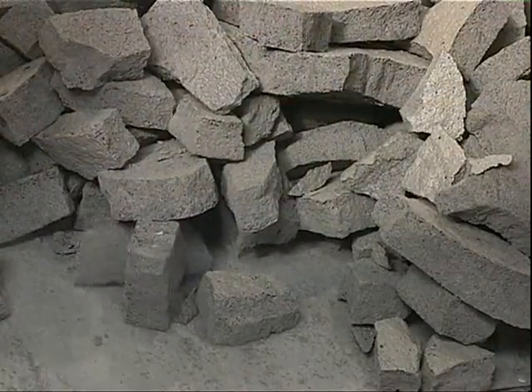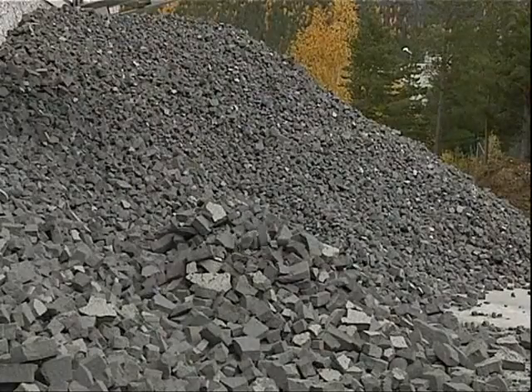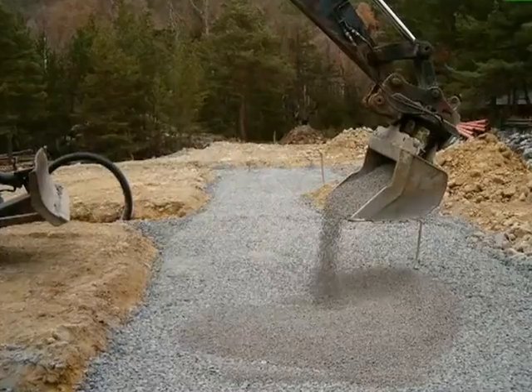Glapor aerated glass is an insulating material with an aerated, frothy texture. Between 10 and 20 percent is made up of recycled glass; the rest is air, contained in a sealed cell structure. As well as the excellent properties glass is known for, the air trapped in the product structure ensures an insulating quality which cannot be beaten.